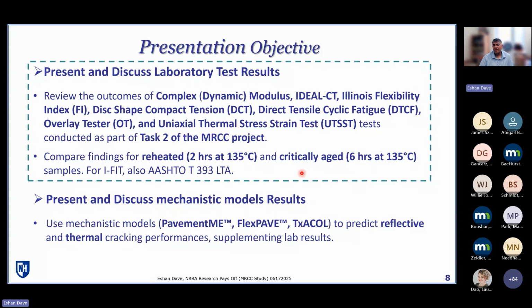On top of that, for the Illinois Flexibility Index test, Illinois DOT conducted that test. They also did what is their default as part of their BMD and mix design acceptance approach, where they actually compact or age their compacted, finally prepared flexibility index test specimens. So they also did that long-term aging in addition to these two conditions. So you'll see those results as well.